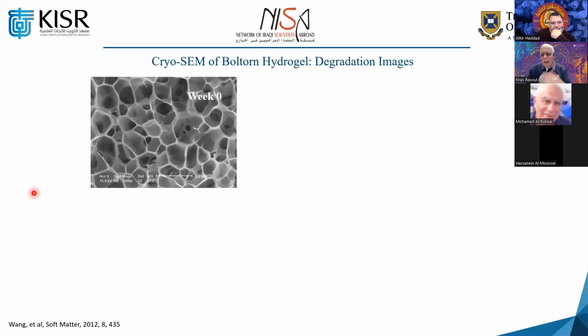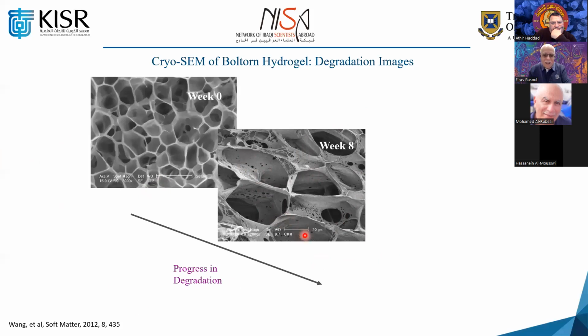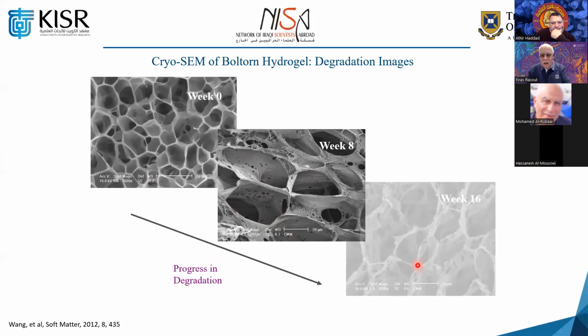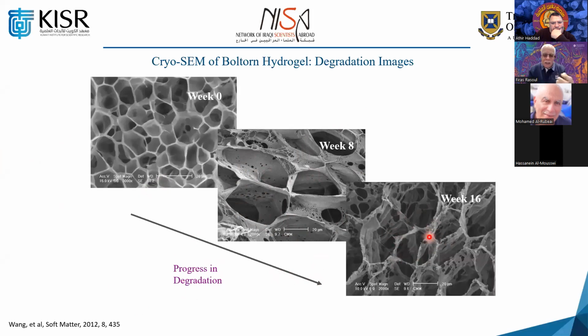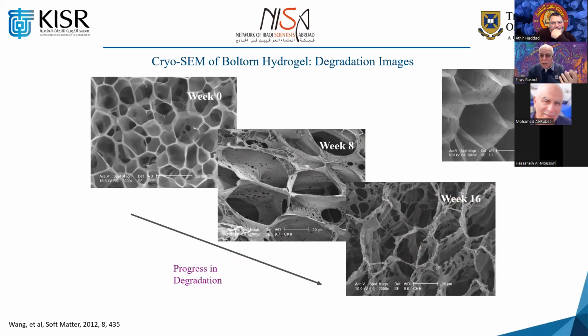Now we look into how the morphology changes. If you go from 0 weeks to 8 weeks, you could see there is pitting inside. This is SEM. And then if you go to a longer 16 weeks, you could see the polymer start to fall apart. And the fantastic thing we saw, which I think was published in the journal Soft Matter, on the first page, you could see how the pitting starts to happen initially. This is after a couple of days, you know, 3-4 days, I think. You could see the pitting on the surface, showing how the degradation started and begins to fall apart. So this is really where we are with this material.